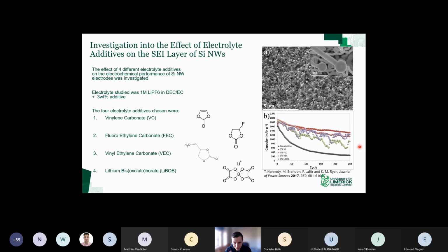Daytime temperature is higher, you get a higher capacity. So the VEC and the LiBOB were much more affected by temperature than the rest, and basically we didn't show this, but other groups had shown that the reason for that is the SEI layer has an Arrhenius dependence. So the lithium diffusivity through the SEI layer has an Arrhenius dependence, and that's more affected by those two electrolyte additives.